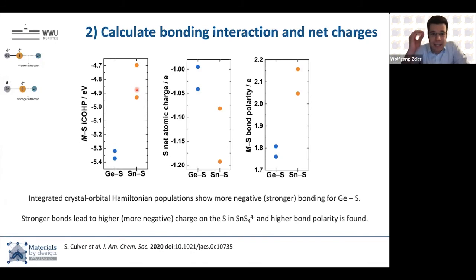If we calculate net atomic charges, we see that the sulfur that is bonded to the tin has a higher negative charge density. And we also see that there's a different bond polarity. The germanium-sulfur bond is a lot less polar than the tin-sulfur bond. So this all falls into place with the idea that we should have more electron density on the sulfur if we have tin, the bond is weaker, and this ideally has a higher charge density, as I said.